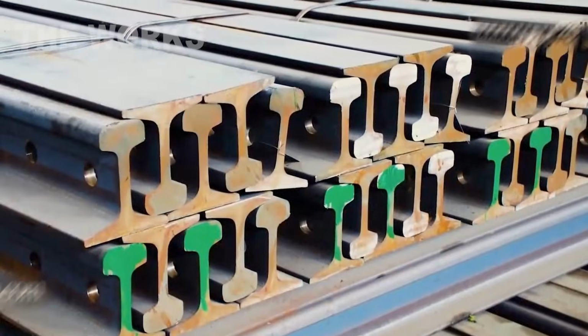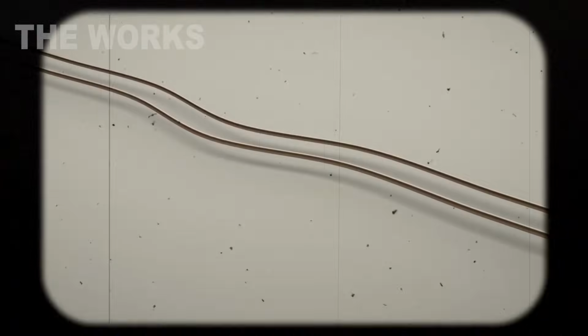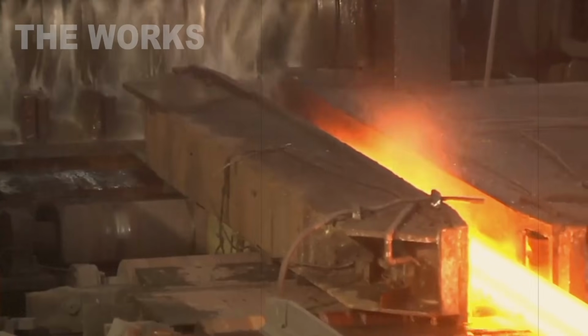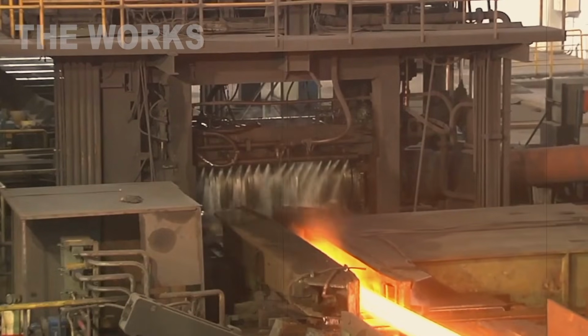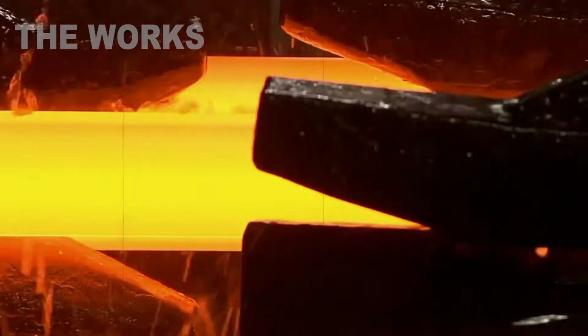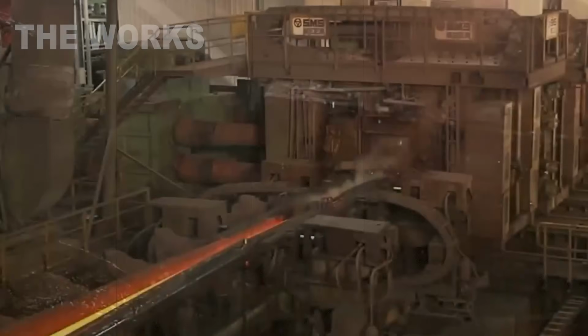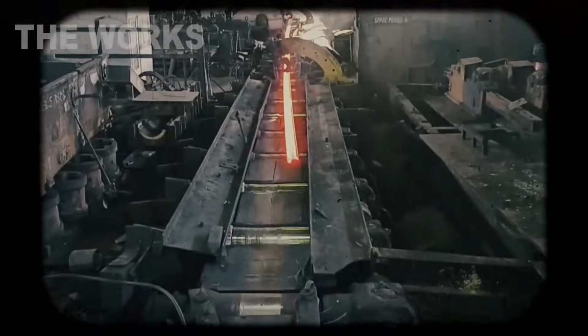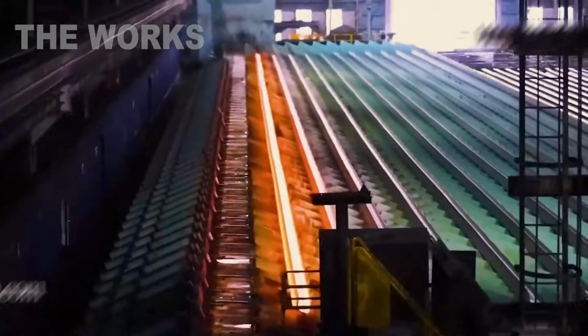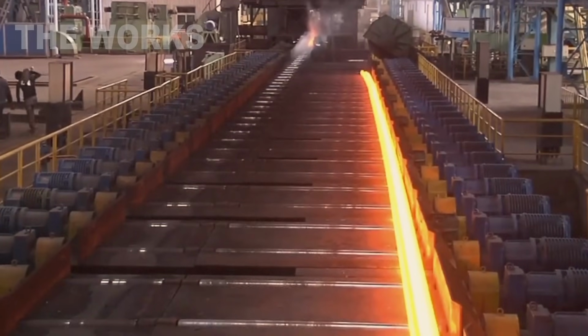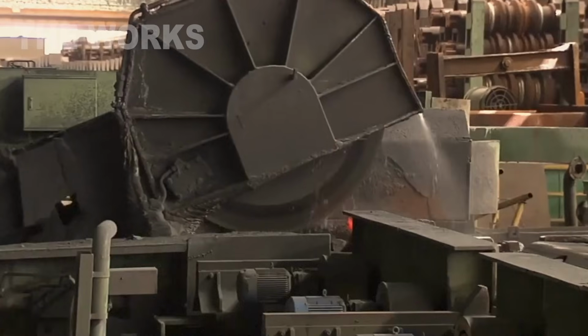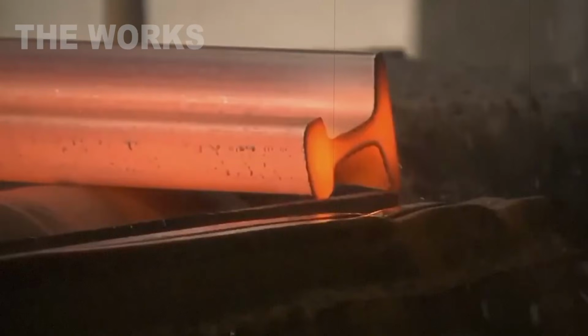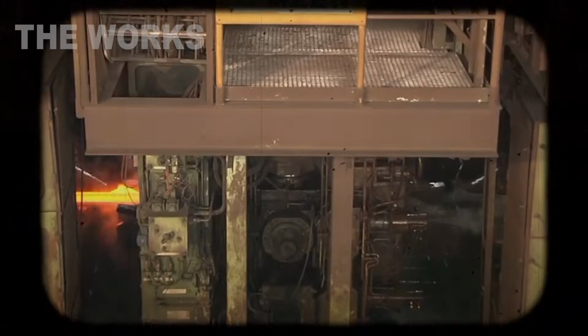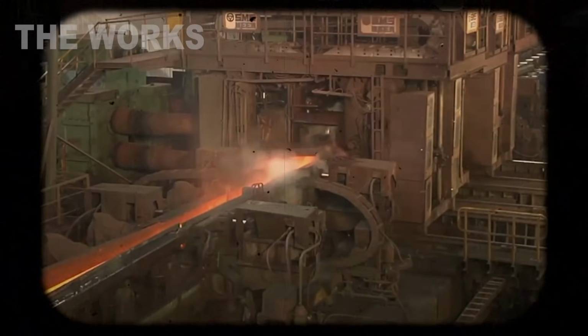This is where heat treatment comes into play, which gives the rail strength, wear resistance, and durability. And it looks almost like a metallurgical spa session. The rail is rapidly heated to high temperatures, about 1,832 degrees Fahrenheit. This is done in furnaces up to tens of meters long, where the temperature is controlled with degree precision. At this point, the crystal lattice of the steel transitions to a new state, austenitic.